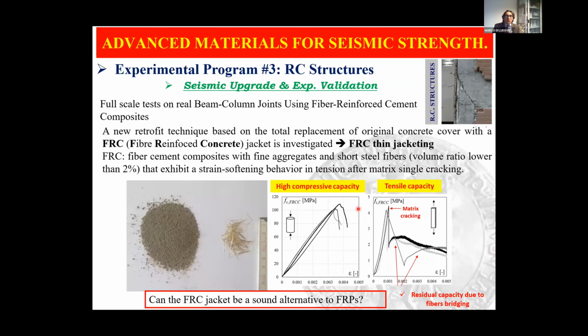And then what we did was to remove the concrete cover and use as a retrofit technique an FRC jacket, so a thin jacketing made by FRC with steel fibers in a volume ratio lower than 2%. Here you can see the steel fibers, the compressive behavior of this system and the tensile behavior, which is characterized by a residual capacity due to fiber bridging, which is very important for this kind of application.